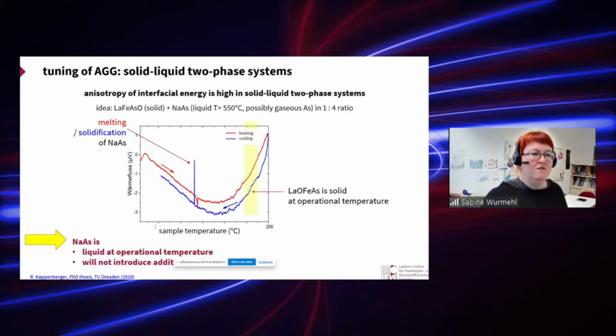We only have liquid sodium arsenide at the operation temperature and solid target material. This is shown here by a measurement of the enthalpy as a function of temperature, red heating and blue cooling curves, where you see sodium arsenide melts at 550 degrees C, and at the operating temperature you are well in the solid state of the target material.